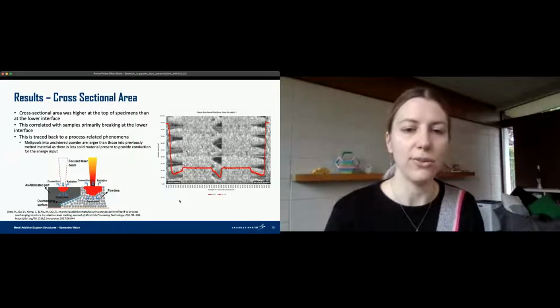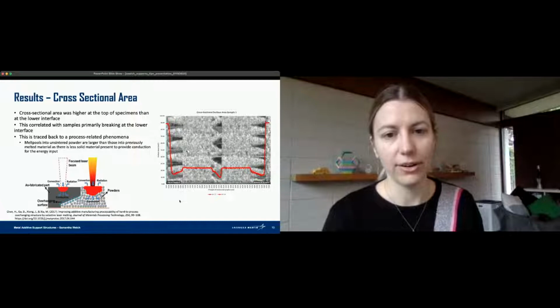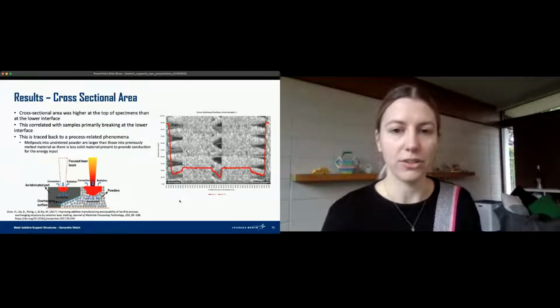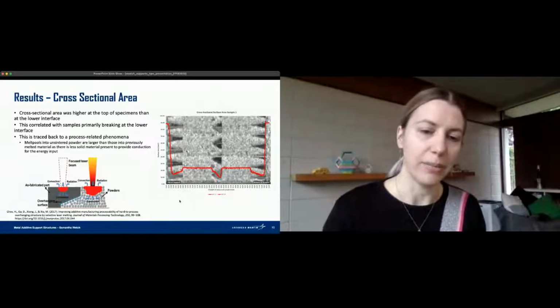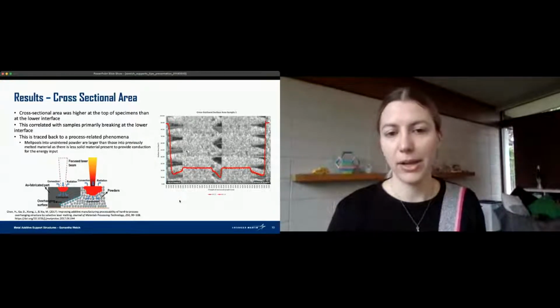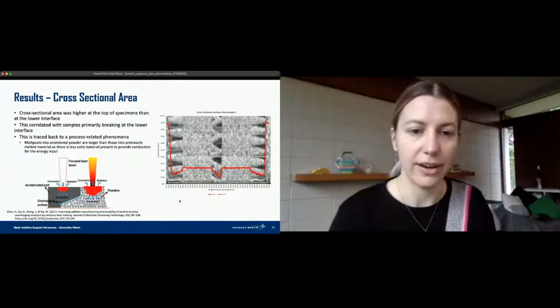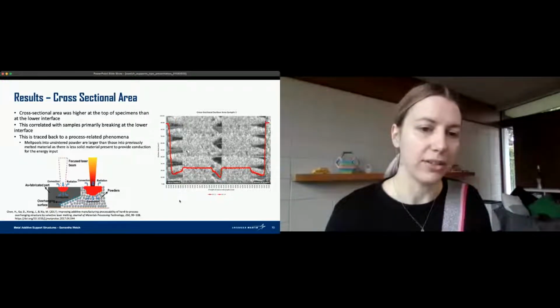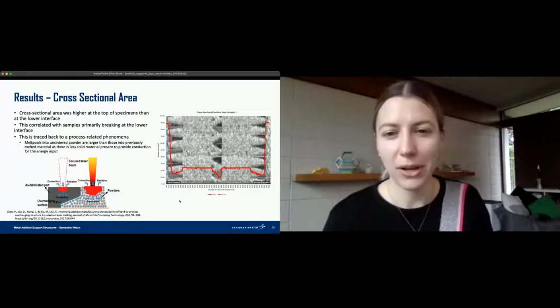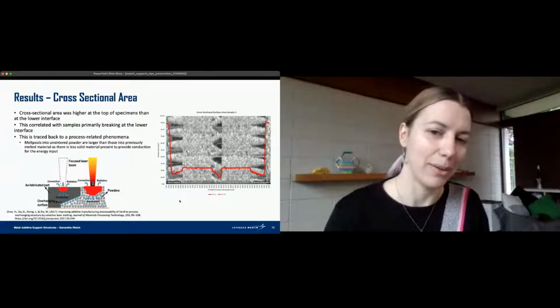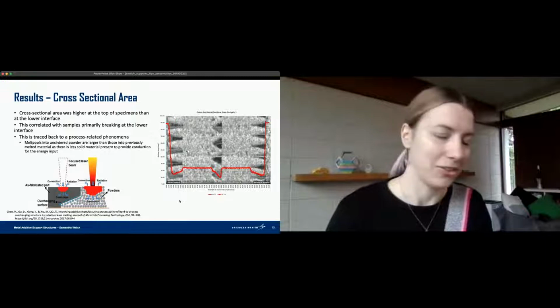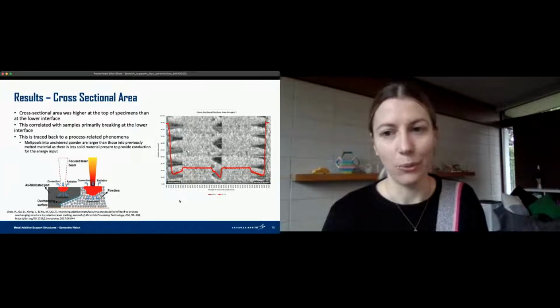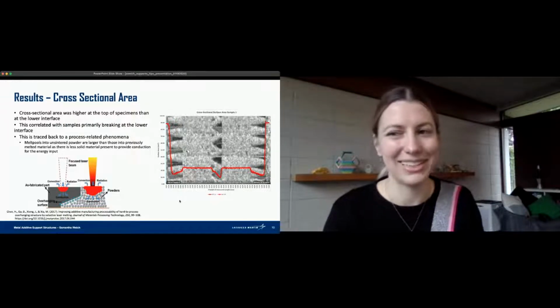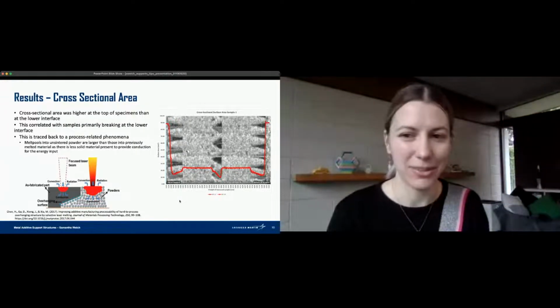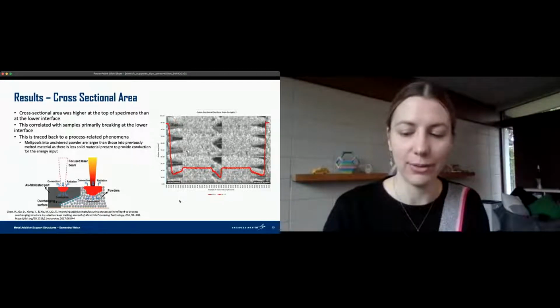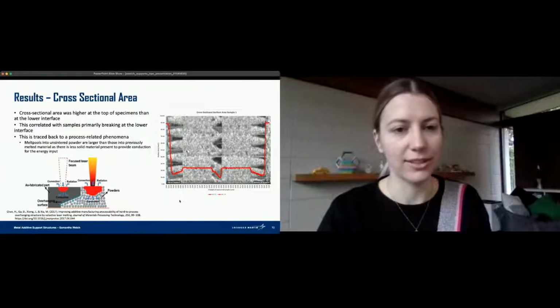And this actually traces back to a phenomenon from the laser process itself. Similar to earlier, where we talked about how the function of these supports is to wick away that thermal energy as it's being dumped in. When we are melting unsintered powder, the melt pools are actually larger because they're spreading more into the neighboring area and not being wicked away into a solid substrate. So those larger melt pools translate to the cross-sectional area of the top of the part being slightly larger consistently, and therefore, because the cross-sectional area is larger, it's not the weakest point in my tensile bar. Physics still applies no matter how complicated the shapes we're printing, and the bottom of the support is going to be my weaker interface. So that was a good find. It was something good to keep in mind as we're approaching these.